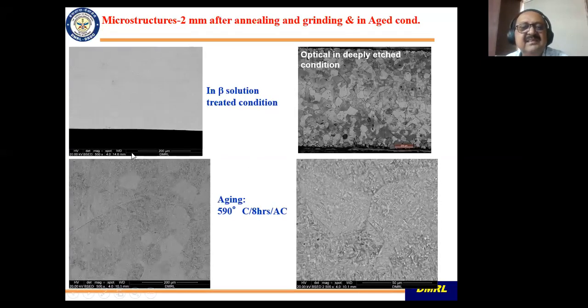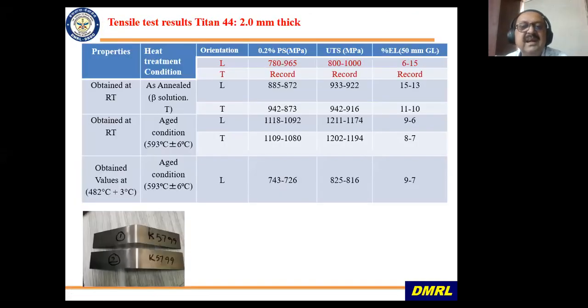And this is the microstructure. This is a single phase beta 21S. So that is why you have no contrast. You have to etch it to get contrast. This is in SEM, so there is no compositional contrast, so you will not get any contrast. You etch it, you start getting contrast. This is an optical picture. This is again an SEM picture, and you can see the very fine precipitation of alpha, which gives beta alloys the strength. Here are the properties.